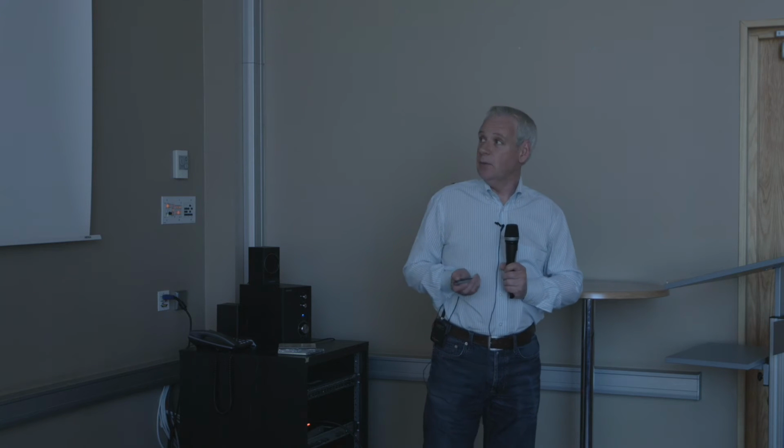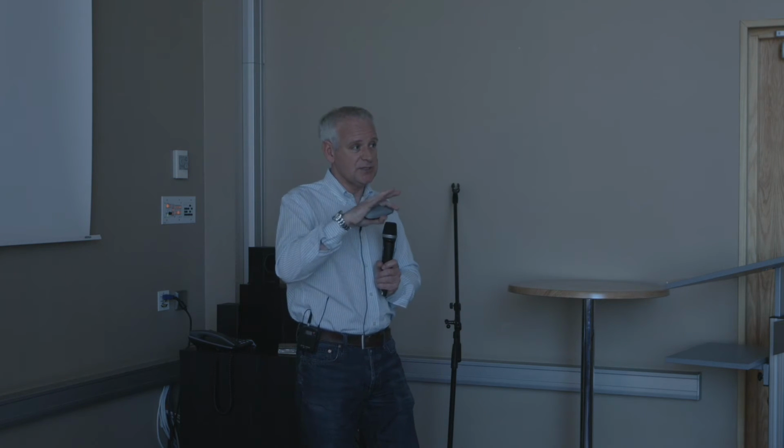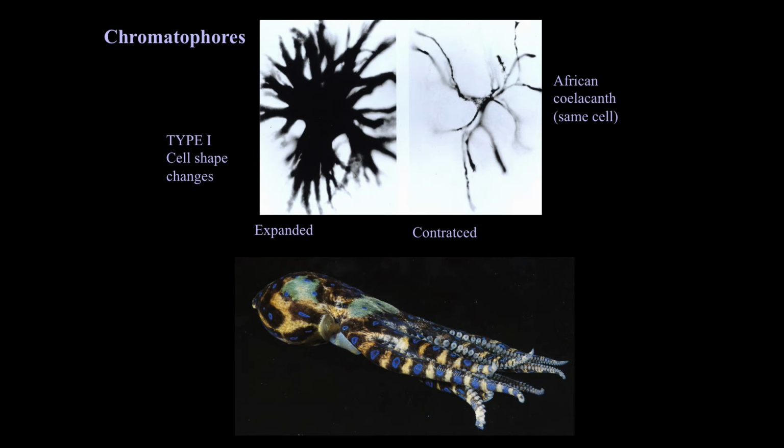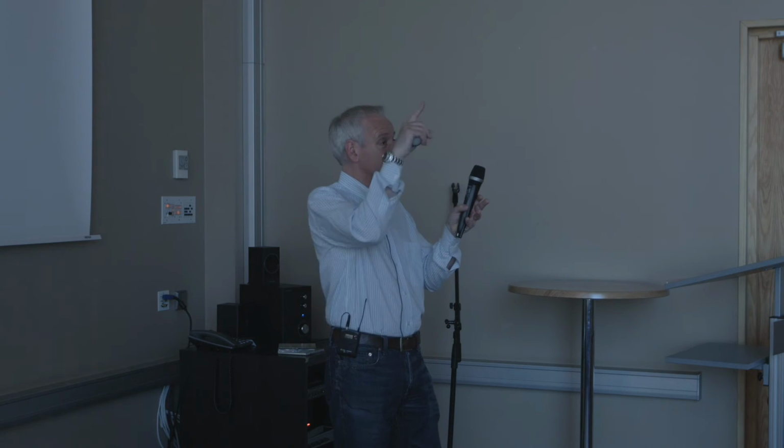That's true to a degree, except that we're now finding that chromatophores are involving mainly yellows, oranges, and reds, and the rest is down to mirrors. This one, actually this is a blue, but actually it's not a blue chromatophore. This is the blue-ringed octopus, whose blue rings light up when the animal becomes aggressive. But the blue is a structural colour, and it's the background that changes. The background can be white normally, so the structural colour is reflecting the blue, but the other wavelengths are passing through, being back reflected. So the whole thing appears a bluish white. But then when those chromatophores expand and the background becomes black, it absorbs all the rest of the colours, so only the blue is reflected, and it comes across as a really bright electric blue.